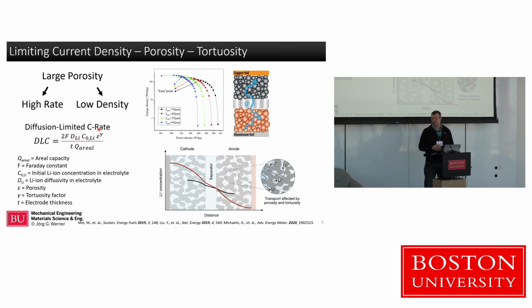So the C rate, or charging rate, is how we classify in batteries how quickly we're trying to charge or discharge the battery. It's relative to how much energy the battery can hold in the ideal case, let's say when you charge it very slowly, right? And C rate is inversely proportional to time. So a C rate of 1 means I'm trying to charge my battery in 1 hour. It's based on hours. A C rate of 10 means I try to charge my battery in a 1/10 of an hour, so 6 minutes, very fast. A C rate of 0.1, or 1/10, means I'm trying to charge my battery over 10 hours.